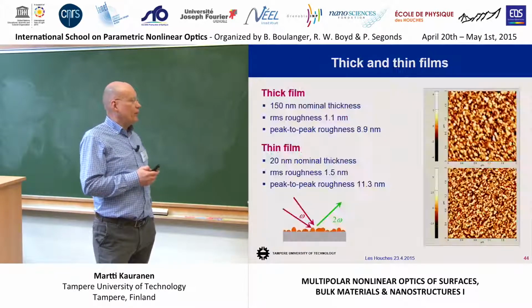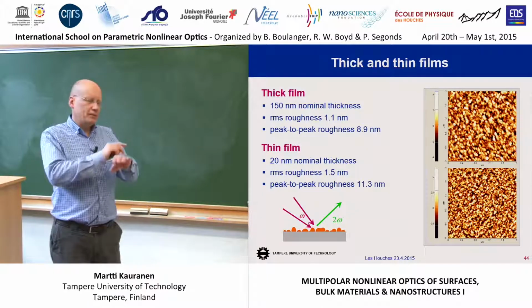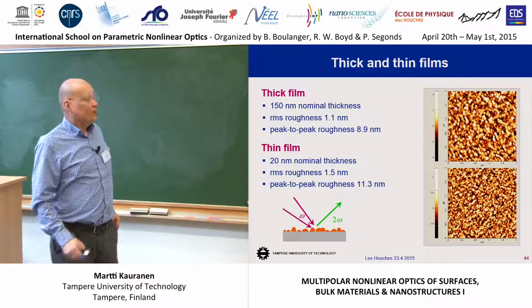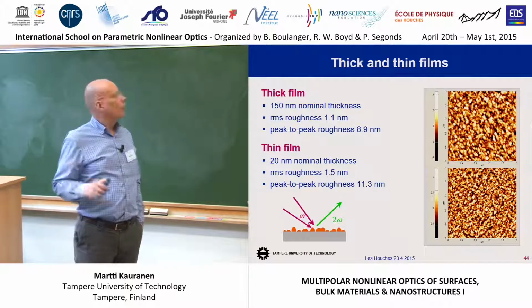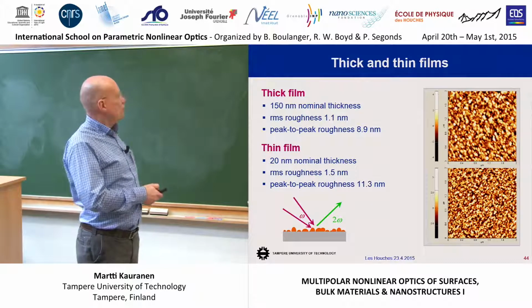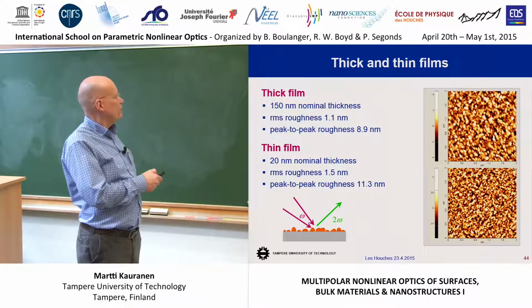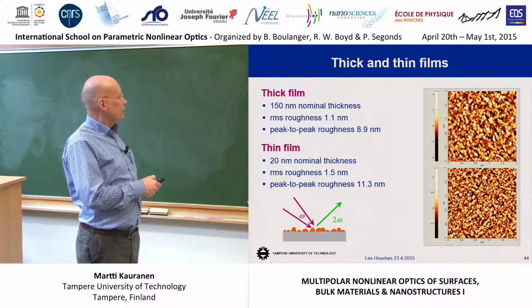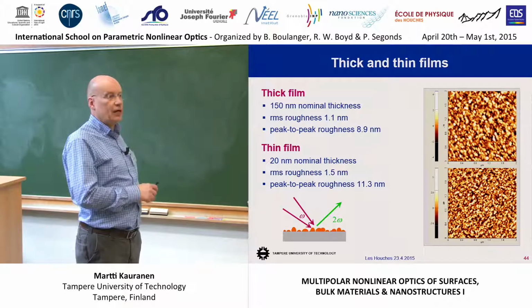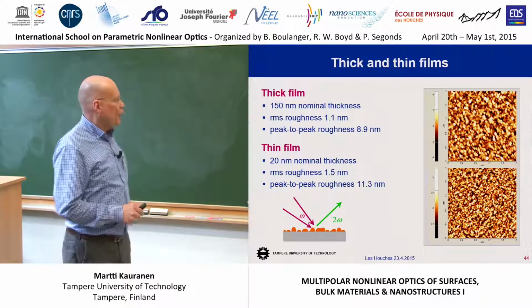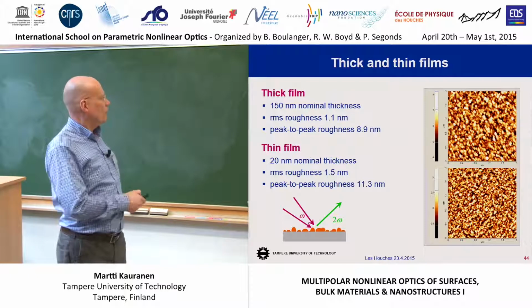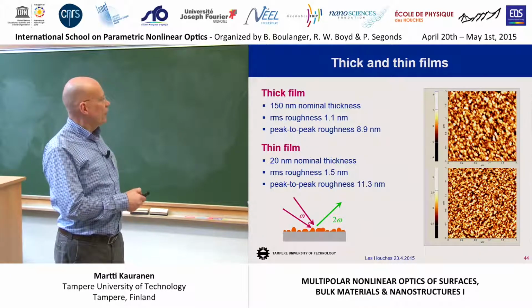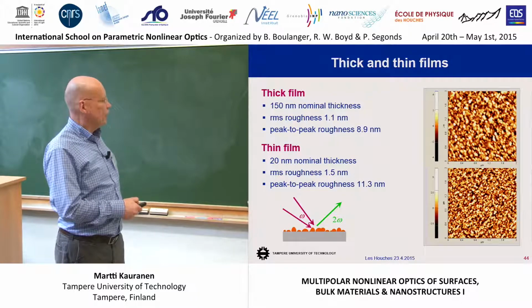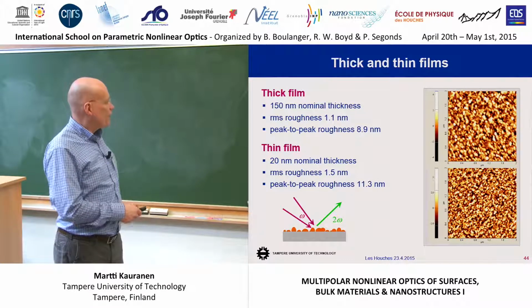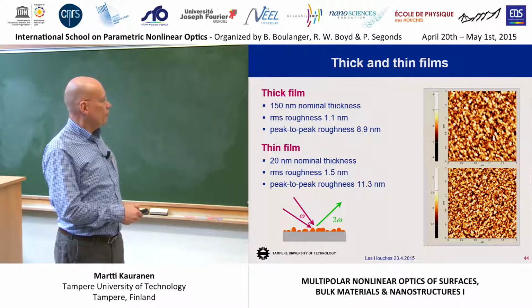But then we thought, okay, let's do another check, because when you make these metals by evaporation, there's always some surface roughness. The film we used in the previous measurements was 150 nanometers thick. There's an RMS surface roughness of 1.1 nanometers and peak-to-peak roughness of about 10 nanometers, which is actually quite a bit. We made a nominally thinner sample, 20 nanometers thick, so then the RMS roughness becomes a little bit higher, 1.5 nanometers, and peak-to-peak roughness is a little bit higher.